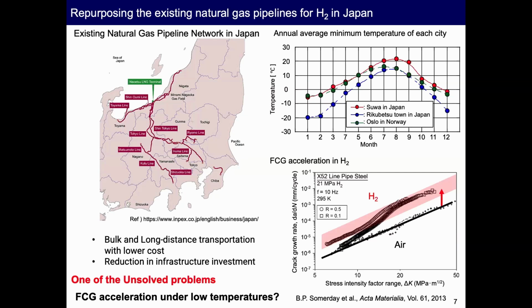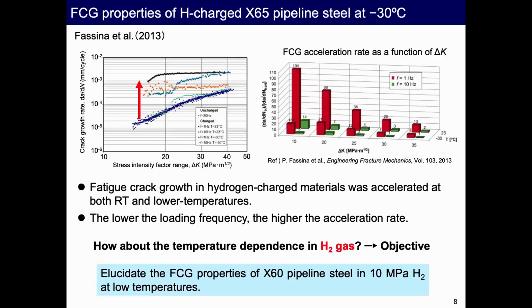But if we look at the climate, in some cities we experience very cold temperatures. In Japan, we sometimes experience minus 20 degrees C or minus 30, even lower. So to ensure the safer use of the pipeline, maybe we need to obtain experimental data at various temperatures. And it is well known that the fatigue crack growth rate drastically increases in hydrogen gas. Some people are trying to investigate the effect of temperature, but under cathodic charging, not in hydrogen gas.